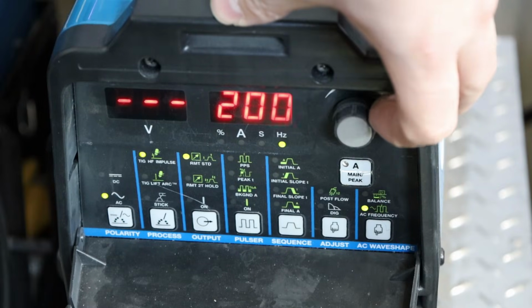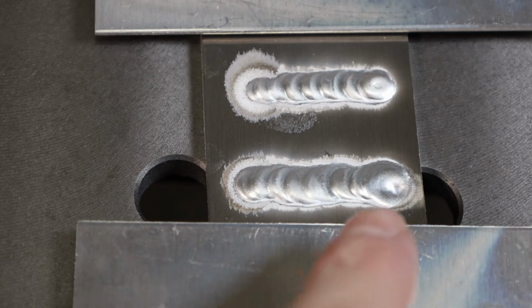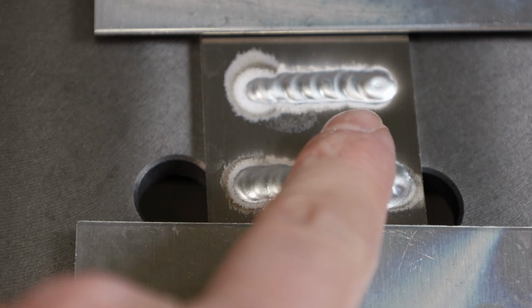You can see, first of all, you can hear the difference. It's running at this lower frequency, like you hear transformers buzz from the 60 hertz there. But I get a nice wide bead, and this can help penetrate a little bit deeper on some material. Contrast this with, I've turned it up to 200 hertz here, and as I weld with this, you can see that the bead is just narrower and more focused. But again, I wouldn't spend a lot of time on this till you get your skill down. So it's just interesting to know that that's a knob you can turn to get a little bit different result. If we look at them here, you can see that we have a wider bead with that 60 hertz compared with the narrow bead at 200 hertz.